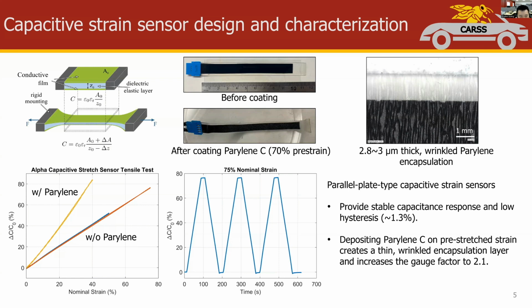To make a stretchable encapsulation layer, we decided to use Parylene first, since it's biocompatible and it has good hermeticity. We first pre-stretched the sensor and deposited Parylene C on its surface. Upon releasing the sensor, the contraction will spontaneously create wrinkled Parylene structures, as you can see at the right-hand side.